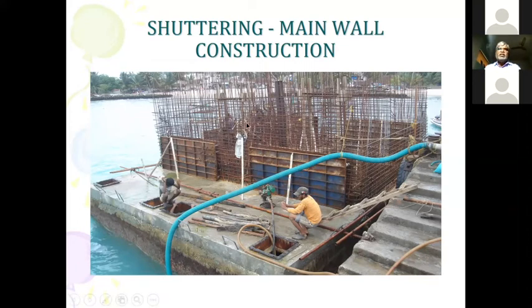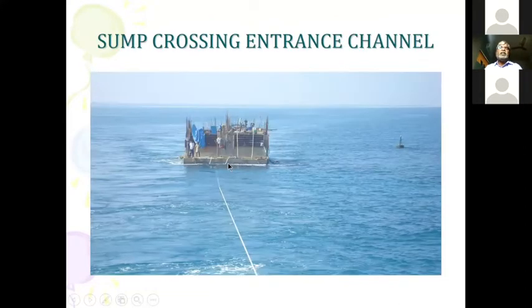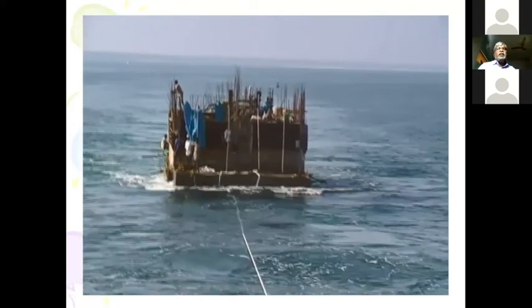Actually, this is the structure we would like to have functionally for using this. We have used completely Tata CRS. I would like to pass on one piece of information: although we bought this corrosion resistant steel well before it was even used, we found that when it was there on the shore itself, despite being CRS, a number of rods got corroded on the shore itself well before it was put into use. So we thought that CRS is going to be a foolproof system where nothing is going to happen, and that was not the case.